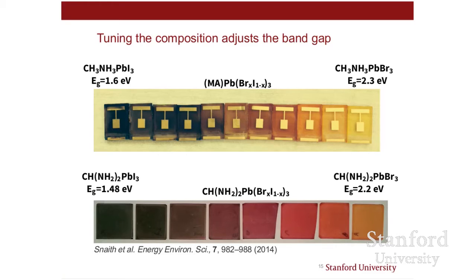If you look at the bottom, we've replaced the methyl ammonium with another organic cation called formamidinium, and you see that that can drop the band gap from 1.6 down to 1.48. Later in the talk, I'll show you that we can replace lead with tin. And so by changing all of the elements in the formula ABX3, we have a variety of knobs for adjusting the band gap for whatever application. And by the way, if you use chlorine, you can raise the band gap all the way up to 3 eV, and you can also make red, green, and blue LEDs, but that would be a topic for another day.